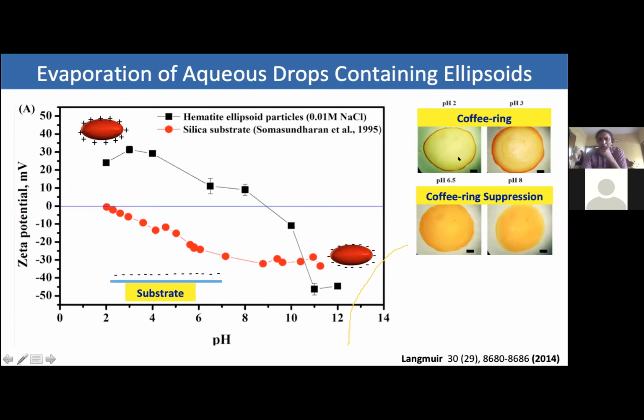So this is the overview of the result. What you're looking at is the deposits that form at pH 2 and pH 3, and they are classic coffee rings. That means there's a deposition of particles at the edge of the dried drop, both for pH 2 and pH 3. However, if you take pH 6.5 and pH 8, you see that there's a more uniform deposition of particles throughout the deposit. So if I take the case corresponding to pH 2 and pH 3, when the particles are highly charged, we seem to be getting a coffee ring. And if you take a case where the particles are weakly charged and the substrate is reasonably charged, we seem to be getting a coffee ring suppression.